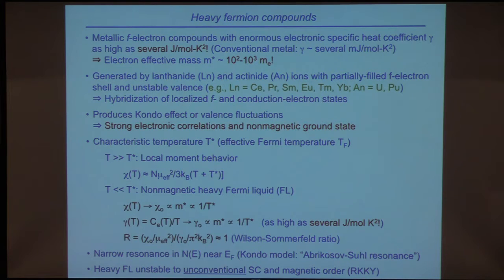These are metallic f-electron compounds with enormous electronic specific heat coefficients, gamma, as high as several joules per mole Kelvin squared. And just to remind you, in a conventional metal, gamma is a few millijoules per mole Kelvin squared. So this can be 1,000 times as large. And from this, you can infer an effective mass between, say, 100 and 1,000 times the free electron mass. Again, this is generated by these lanthanide or actinide ions with partially filled f-electron shells and unstable valence.